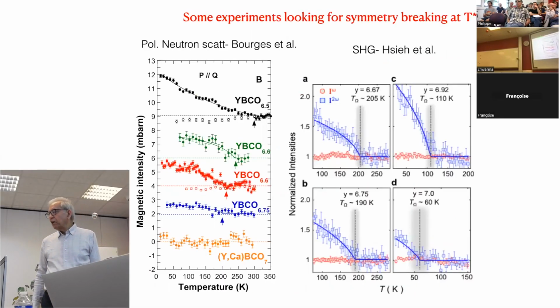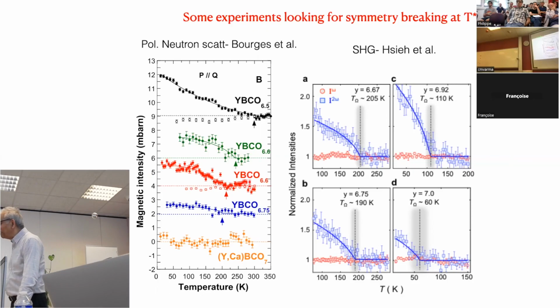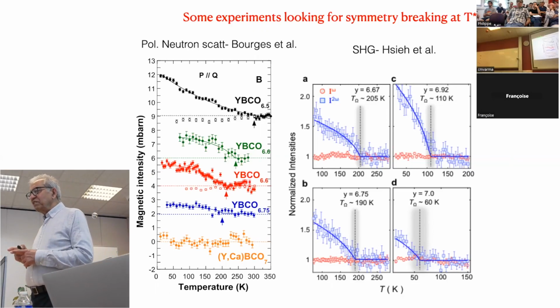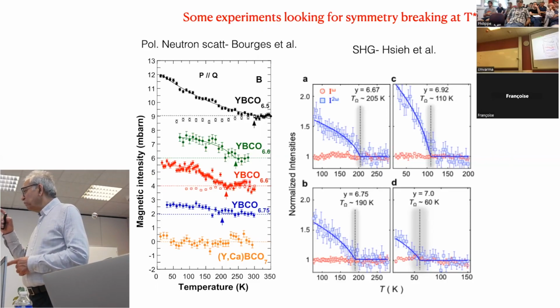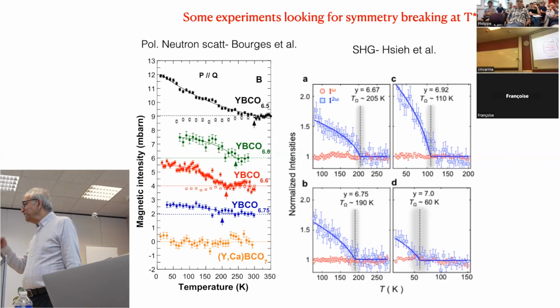Okay, so then the experiments started coming out. I'm going to show you two experiments on the same material. The experiments were first done in Bismuth 2212 by ARPES, okay, by Kaminski et al. But neutron scattering in principle gives you the most detailed information. In practice, bloody hard, because I'm not changing translational symmetry. Okay, so I'm getting some magnetic signal at the same Bragg spots where there is a nuclear Bragg peak, which, for the kind of moments we expect, is a few hundred to 1,000 times larger than the magnetic one, and so one has to do the experiment very carefully.